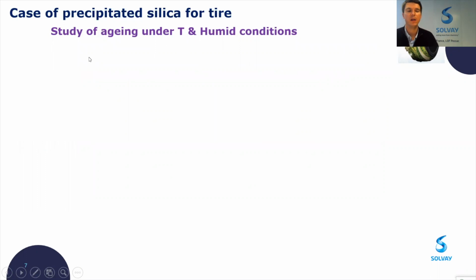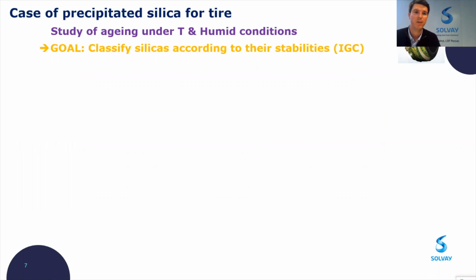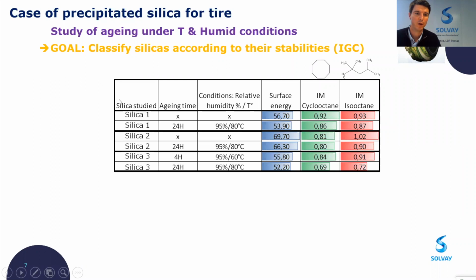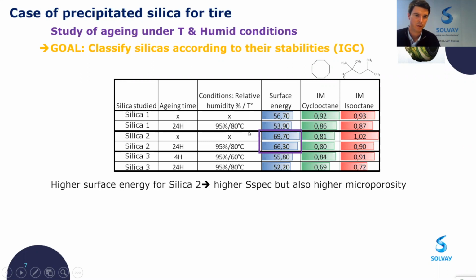So also the IGC is very useful to the study of aging, because silica can be also affected by different conditions in terms of humidity and temperature. And in this case, the idea was to classify silicas according to their stabilities. Once again, we have compared 3 types of silica and performed an aging during 24 hours in this condition of humidity and temperature. And concerning the surface energy, as you can see here, we are able to differentiate the type of silica just with the surface energy. And once again, it's very consistent with the textural properties of the silica.